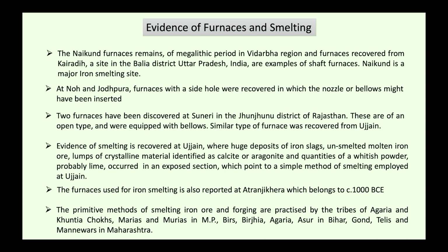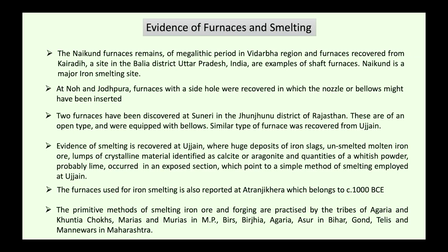Evidence of smelting is recovered at Ujjain, where a huge deposit of iron slag and unsmelted molten iron ore lumps, crystalline material identified as calcite or aragonite, and quantities of a whitish powder, probably lime, occurred in an exposed section, which points to a simple method of smelting employed at Ujjain. The furnaces used for iron smelting are also reported at Atranjikhera, which belongs to circa 1000 BCE,